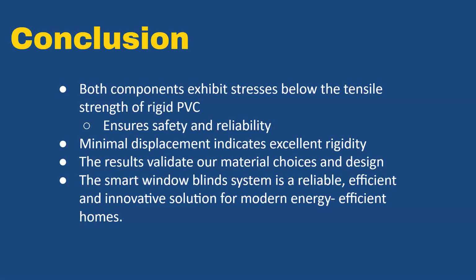So in conclusion, I can say the results from the stress analysis show that both the linkage and the bar component exhibit a maximum value of von Mises stress that is below the tensile strength of rigid PVC, which is 4.6 times 10 to the power 7 Pascal, or approximately 6,672 psi. The linkage experienced a maximum stress of 5.255 times 10 to the power 2 psi. The bar experienced a maximum stress of 1.169 times 10 to the power 2 psi. Both values lie far below the tensile strength of the PVC material. Additionally, the maximum displacement indicates that there is excellent rigidity and minimal deformation when under the applied load of 15 pounds.